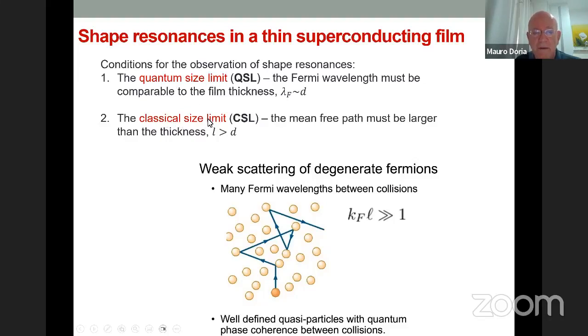But there is also the classical size limit, which means the following. You may have a very small particle, but let's take a thin film. The energy levels are like a string, you have the very spaced energy levels. However, if the electron, when it goes from one side of the film to the other, suffers many collisions, then all this structure is destroyed and you don't see it. So you have to have that the mean free path is larger than the size of the system, such that you don't have collisions happening in between. So that's the two limits.